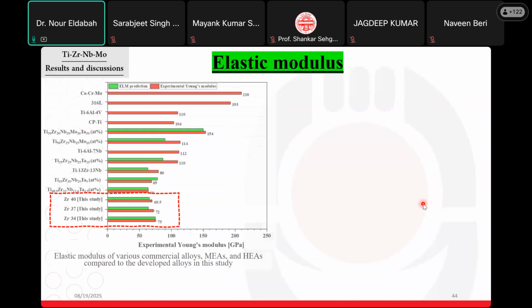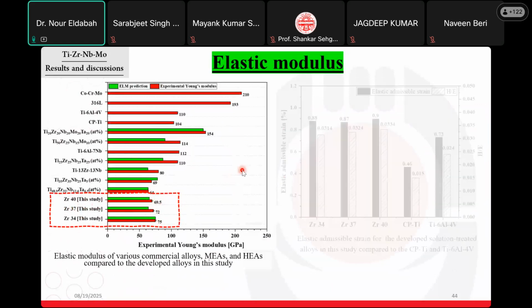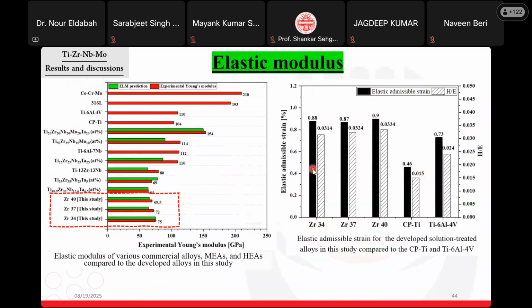For the elastic modulus, all three alloys, especially the zirconium 40 alloy, which is our focus, are around 69.5. The red line here, or the red column, indicates the experimental value, which is very near to the prediction of the neural network for all three alloys. Any questions?